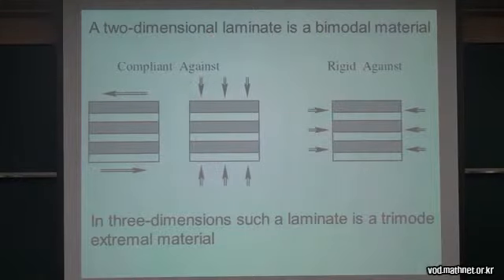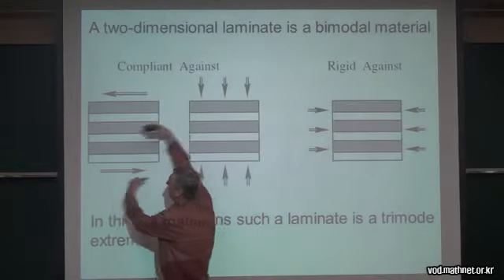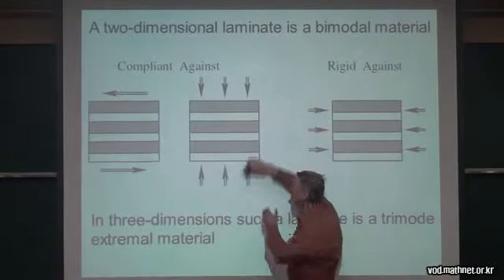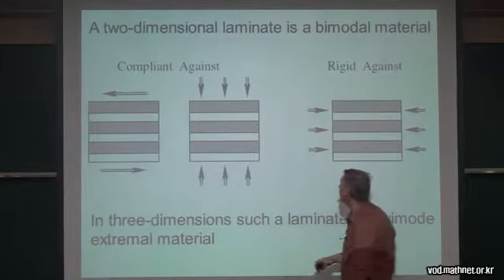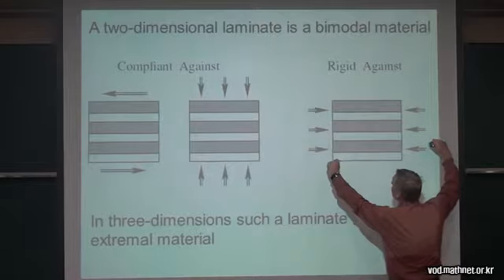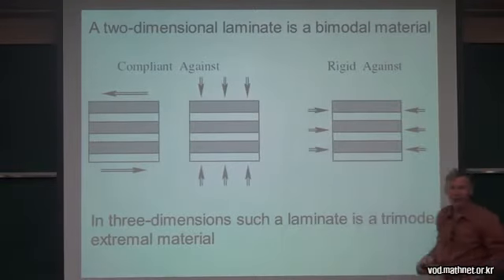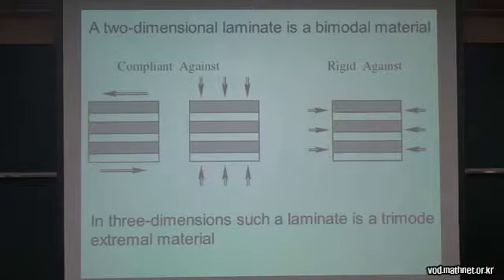The simplest geometry is a laminate material, where you've got very stiff material mixed with very compliant material. It's easy to take this material and shear it back and forth in this direction. You can also easily compress it back and forth in that direction. If we're in 2 dimensions, however, it's stiff against this sort of loading. So in 2 dimensions, this has 2 easy modes of deformation, 2 small eigenvalues, but 1 large eigenvalue. In 2 dimensions, the elasticity tensor is represented by a 3x3 matrix.